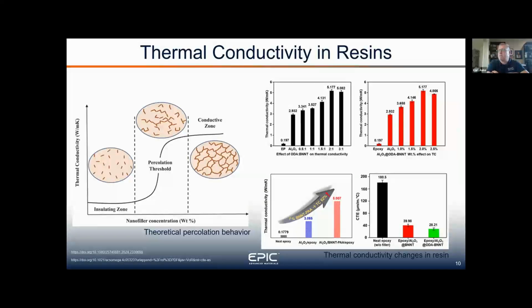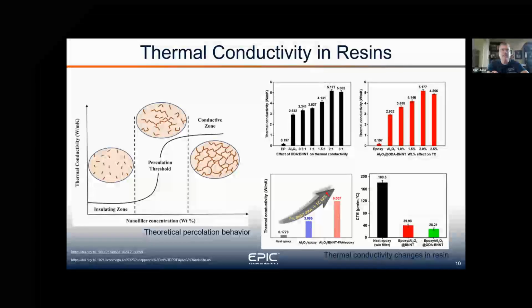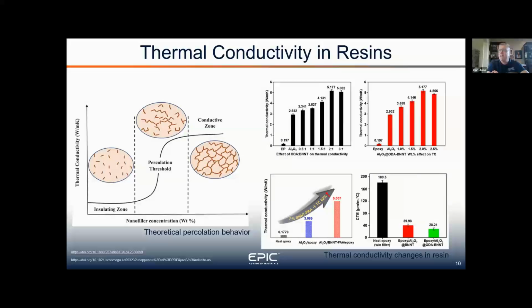Let's talk a little bit about thermal conductivity and how it works. So initially, you have your epoxy resin there on the left-hand side, and it's basically an insulator. Start adding BNNTs, and you start getting to a percolation threshold, which is where the BNNTs are touching each other, and then it creates a conductive zone.